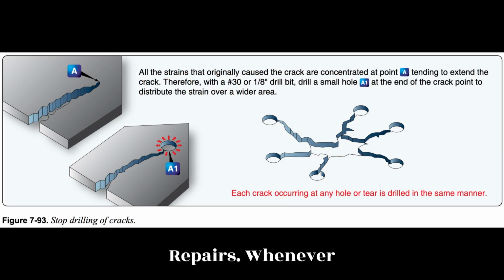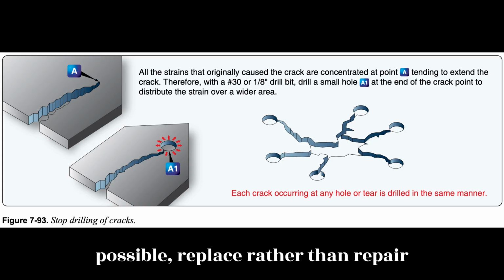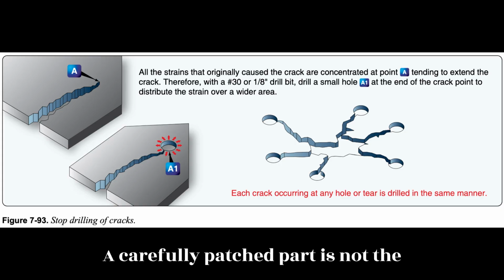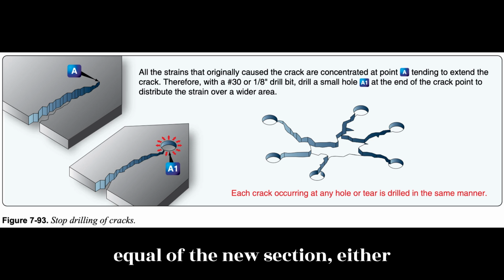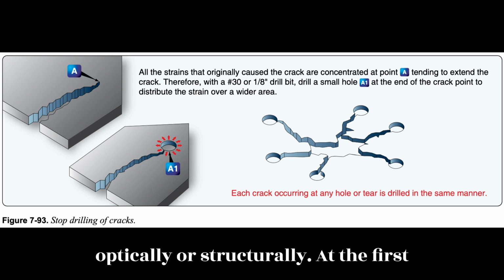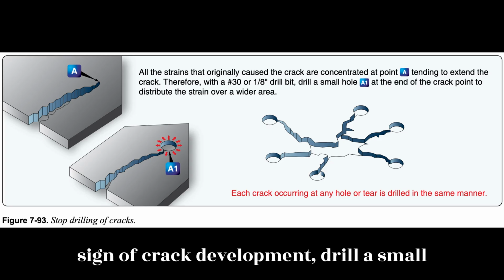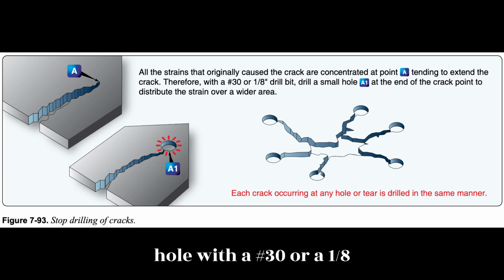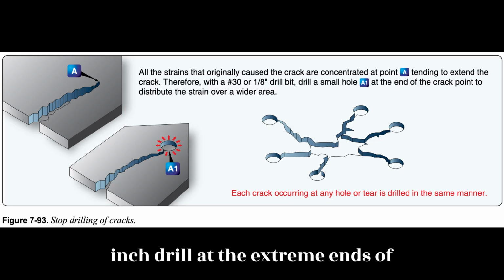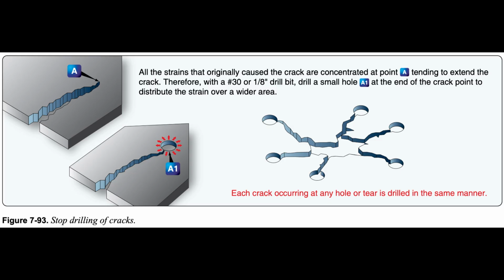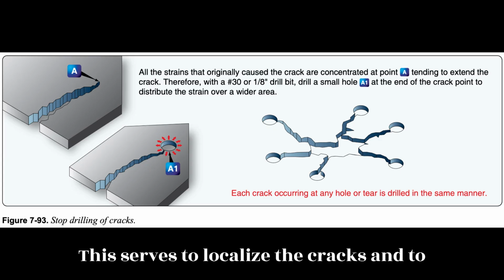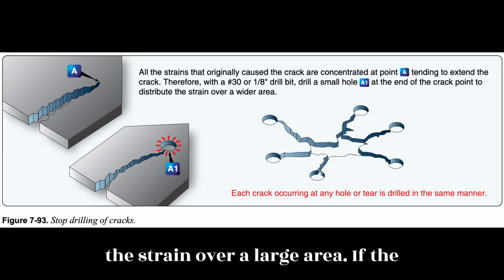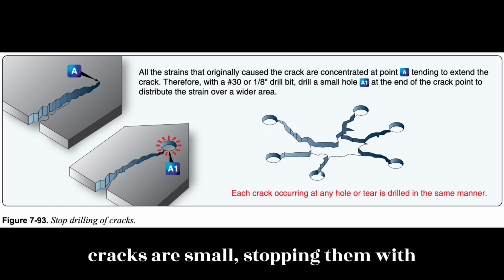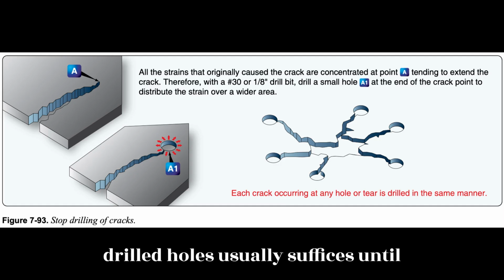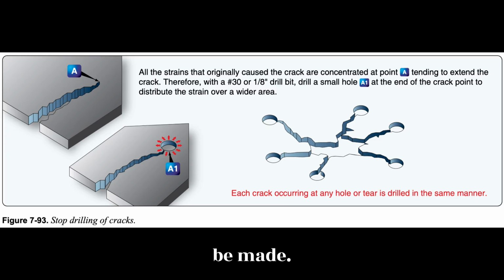Repairs. Whenever possible, replace, rather than repair, extensively damaged transparent plastic. A carefully patched part is not the equal of a new section, either optically or structurally. At the first sign of crack development, drill a small hole with a number 30 or a 1/8 inch drill at the extreme ends of the cracks. Figure 793. This serves to localize the cracks and to prevent further splitting by distributing the strain over a large area. If the cracks are small, stopping them with drilled holes usually suffices until replacement or more permanent repairs can be made.